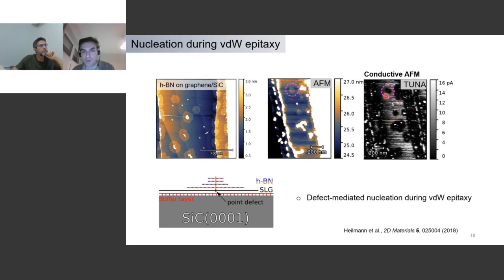Anyway, what I want to show you here, the most important thing, is that even for these beautiful monolayer islands, it looks like in the middle we have a leakage path that allows for conduction in the middle of what is otherwise insulating HBN. And so we propose that even point defects in single layer graphene would be responsible for our nucleation. So we kind of coined this defect-mediated nucleation during van der Waals epitaxy.